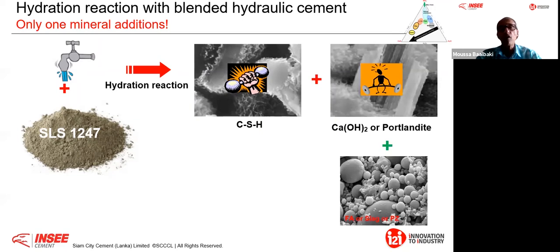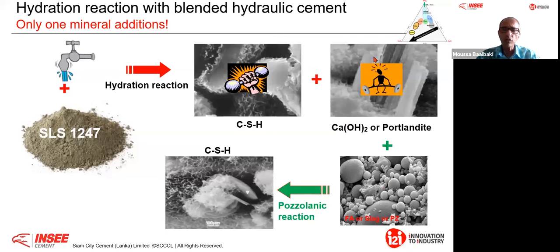Now, of course, in this cement, I have the aluminosilicate material, like fly ash, like pozzolana, like slag. Therefore, you have SiO2. This SiO2 will combine with the calcium, and therefore you have a second reaction called the pozzolanic reaction. And this pozzolanic reaction will turn the Portlandite, that is the weakness in the concrete when it comes to durability, to strength. And suddenly you are mitigating the problem with Portlandite. If you go and ask Port City why they go exclusively with fly ash cement, say, extra, that is the reason. I will explain to you later.